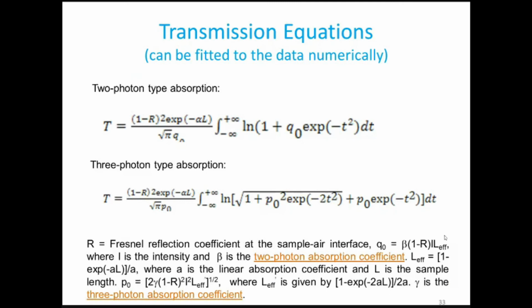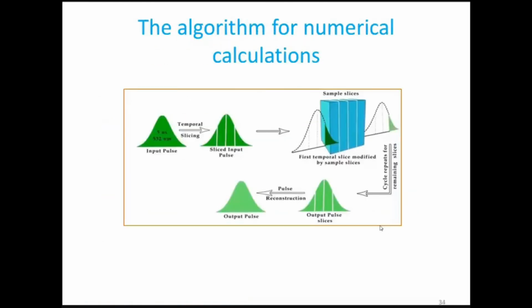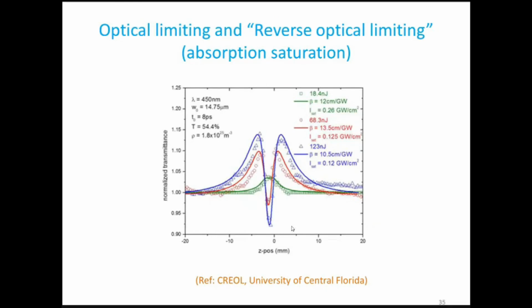So, and there are transmission equations like this which you use to finally fit your data. And from that fitting, this is the algorithm for numerical calculations. And from that fitting, you will be able to calculate the nonlinear absorption coefficient and also the saturation intensity coefficient. So very interesting kind of Z-scan curves. This is a Z-scan curve, an interesting kind of curve because this is different from what was originally published in 1990 by the same people from CREOL. It was from this department where people invented the Z-scan technique.